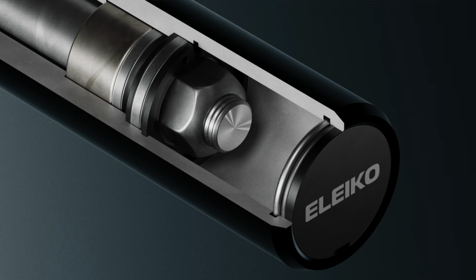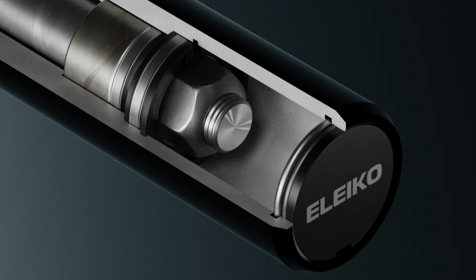Patent-pending geometrical changes have been made to the bars in order to improve fatigue resistance. The center of mass is moved in closer to the center of the bar by increasing the bar flange dimension and removing material from the outer end of the sleeves. This redistribution of mass reduces the forces acting on the critical area of the bar just inside the sleeves when the bar is dropped. As the dimensions of the non-certified bars, so the performance and hybrid bars, are not regulated by any federations, we implemented larger changes in geometry for a more significant fatigue tolerance improvement on these bars.